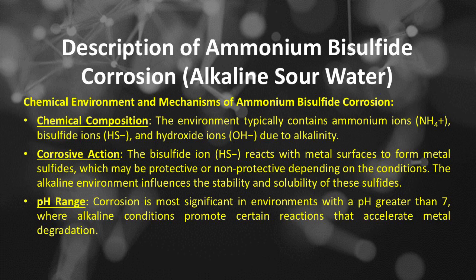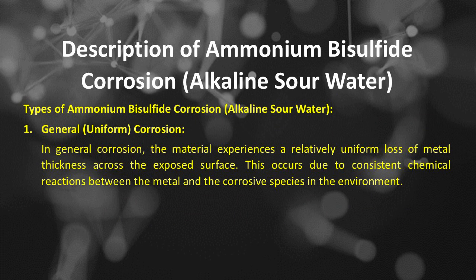pH range. Corrosion is most significant in environments with a pH greater than 7, where alkaline conditions promote certain reactions that accelerate metal degradation. Types of ammonium bisulfide corrosion or alkaline sour water. General or uniform corrosion. In general corrosion, the material experiences a relatively uniform loss of metal thickness across the exposed surface. This occurs due to consistent chemical reactions between the metal and the corrosive species in the environment.